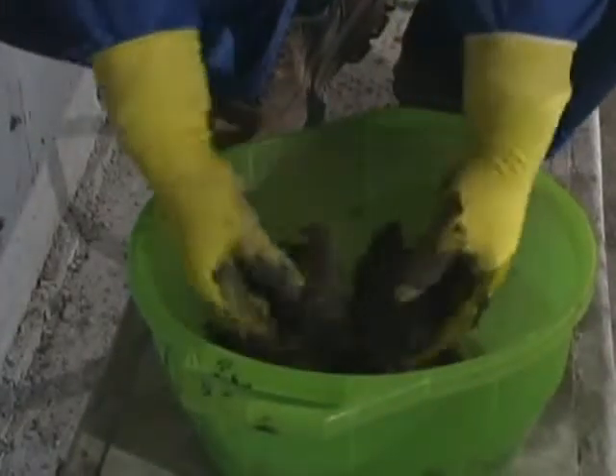of 6 centimeters. If you come across areas with spalling or holes, the surface should be primed with Penetron in the same way. Penecrete should then again be applied in laminating layers not exceeding 6 centimeters until the desired surface profile is achieved. However, make sure to wait between 2 and 6 hours before applying consecutive layers of Penecrete.